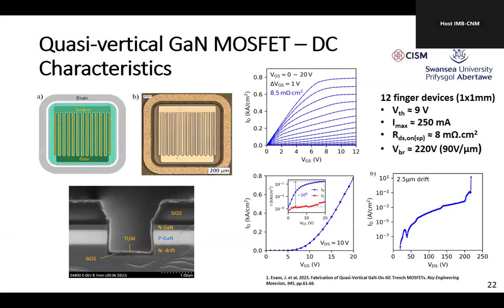What's not shown here is that we extracted the channel mobility from the subthreshold characteristics. The mobility in the channel was, at a first pass, about 20 to 25. And when I think back to silicon carbide days, on a first attempt in silicon carbide you were getting channel mobilities of about 5. So it's already almost an order of magnitude better. So we think we can get very nice channel mobilities, maybe approaching 100, in GaN.